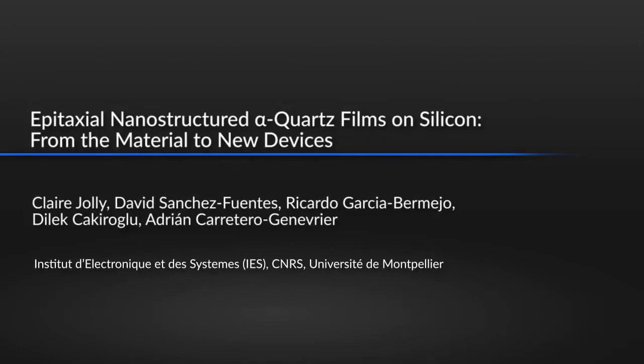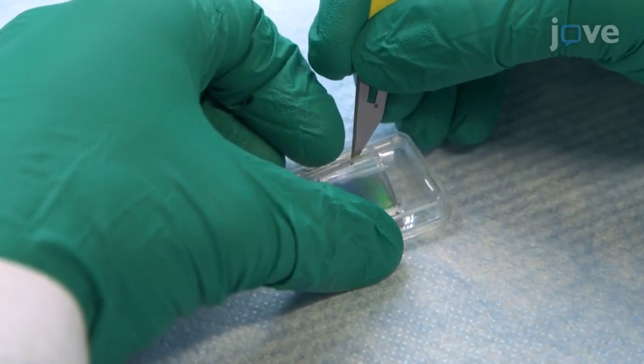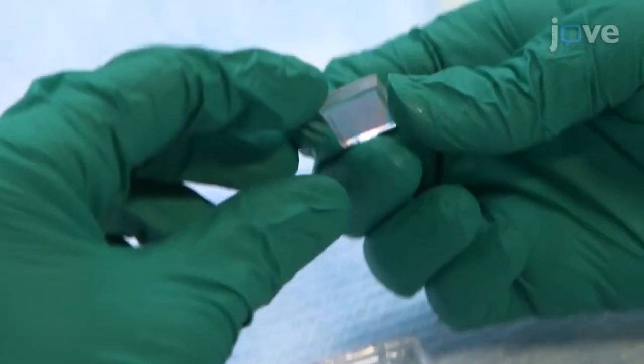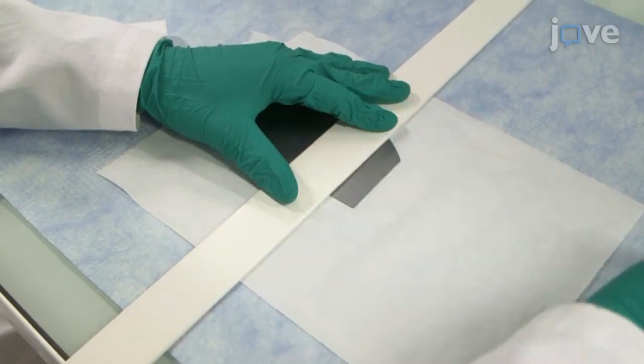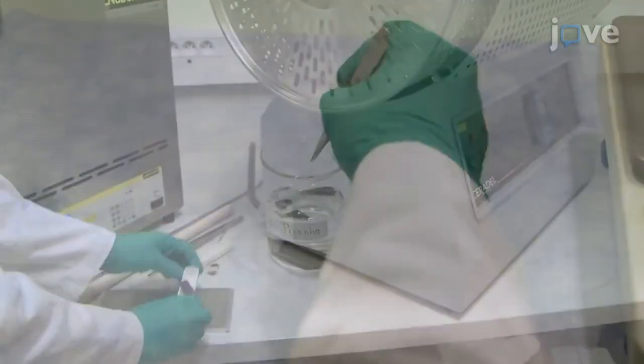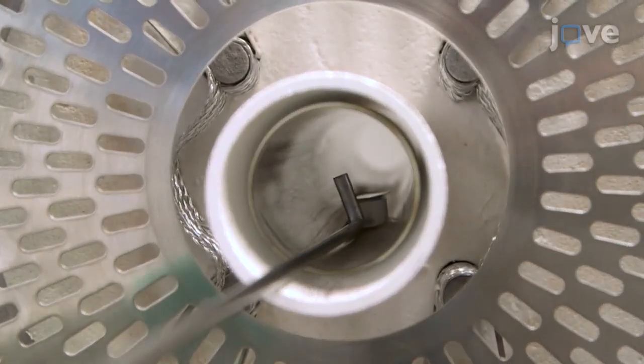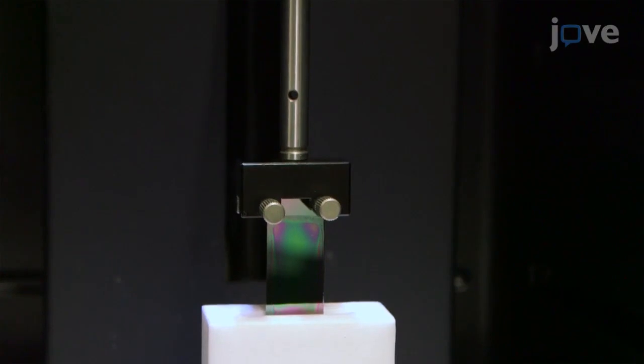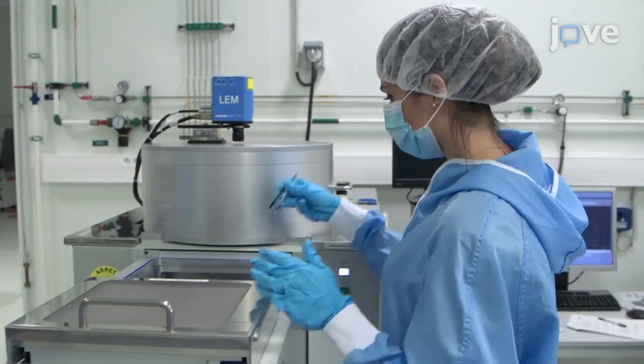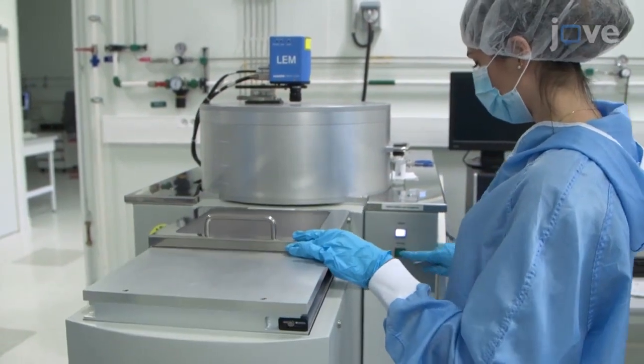Nowadays, quartz-based sensors are limited by the miniaturization process and the monolithic integration of this material on silicon. These bottlenecks are now overcome with the first chemical integration of epitaxial piezoelectric quartz MEMS in the form of high-quality microcantilevers. From a technological perspective, these novel quartz devices open the door to the development of cost-effective active microelectromechanical system engineered from lead-free piezoelectric oxide materials and providing high forces and mass sensitivity while preserving its quality factor.